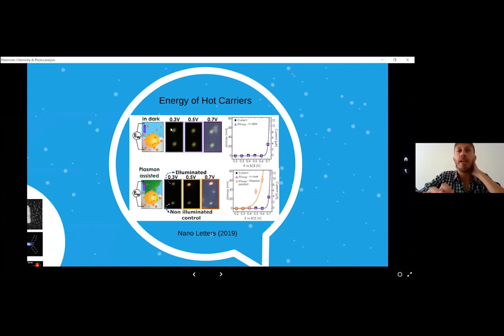Here we have gold nanoparticles, 16 nanometers in diameter, and we applied different voltages until the reaction happens on the surface of the particles. Then we performed the same experiment in the electrochemical cell, but illuminating one of the nanoparticles and keeping the other one as a control. What we could see is that when the reaction takes place, the nanoparticle changes from this green color to this orange color.